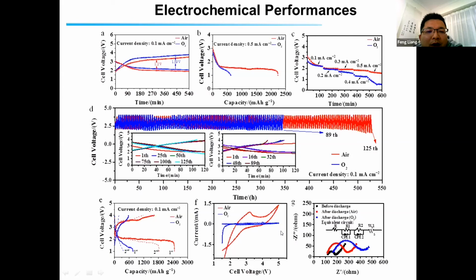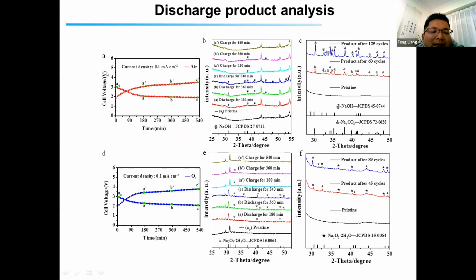So in order to analyze the reason why this sodium-air battery is better than the sodium oxygen battery, we use in situ XRD to analyze the performance of this battery. So this is the discharge result at different states. So from this result, we can see the product of the sodium-air battery is sodium hydroxide. In the case of the sodium oxygen battery, the main product is sodium peroxide dihydrate. So this is the main difference in the discharge product.